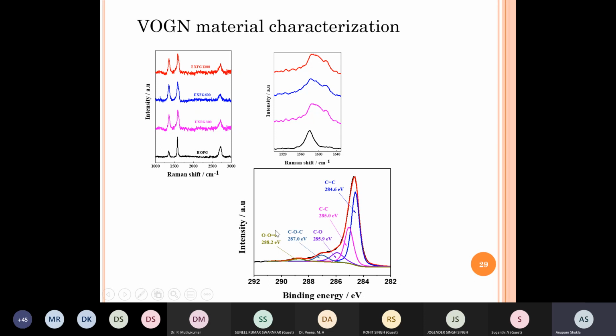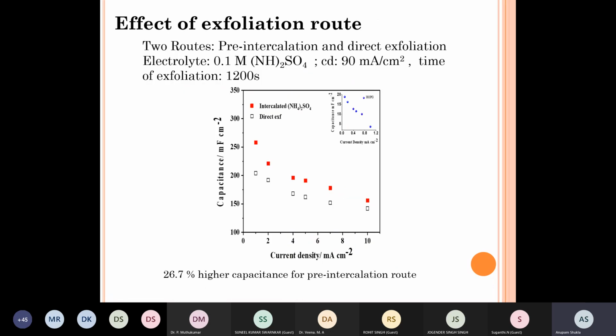They are detrimental in the sense that whenever one gets an oxygenated surface or edge in the graphene, the electronic conductivity goes down. But the positive side is these oxygenated groups can then lead to oxidation and reduction on the surface, so therefore they can provide pseudo-capacitive character. Okay, so different synthesis route that we followed.